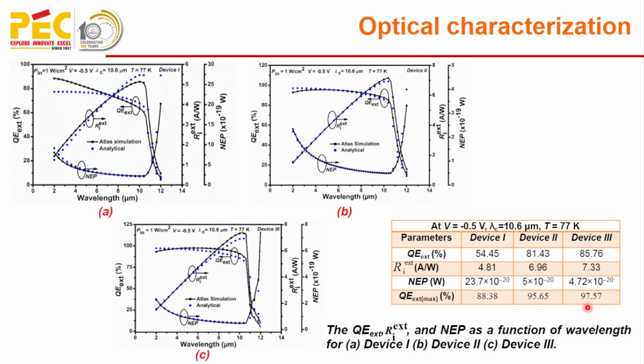So, conclusion. In this work I have designed three different device architectures: device 1, which consists of one heterojunction; device 2, which is a dual junction consisting of one heterojunction and one homojunction; and device 3, which consists of two heterojunctions, in the long infrared region. All the optoelectronic properties were analyzed using computer simulation, which was further validated by the analytical model based on drift diffusion, tunneling and Chu's method.